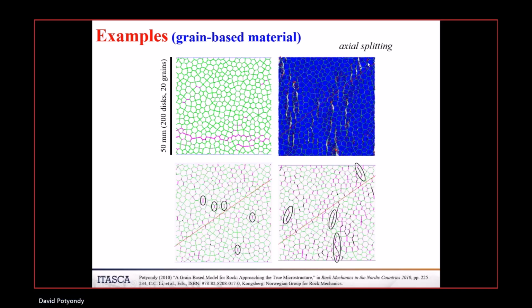This is actually a force chain plot right after the peak. And this force chain plot is using black and blue for compression and red for tension. But the thing that's interesting about it is you can see how this material is dilating as it's beginning to fail. This plot is like an indirect way of drawing this, because we're drawing all those force chains, and because the material is split apart here, there are no force chains showing there. So it pulls out the fact that this is basically breaking into a bunch of parallel columns. So this is actually what we believe is the real mechanism of rock.